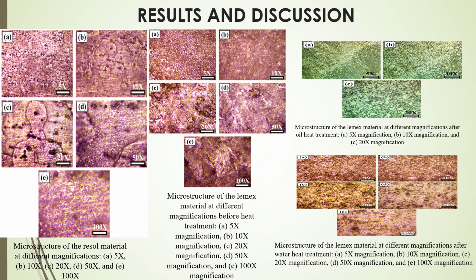After applying oil heat treatment, we observed noticeable changes in the structure at magnifications of 5x, 10x, and 20x. The grains become thinner and more compact, showing improved hardness and wear resistance. In summary, I can see that the heat treatment significantly improved the microstructure of Lemex material, leading to enhanced durability and mechanical performance. This suggests that treated plowshares will have longer service life and reduced wear in agricultural use.